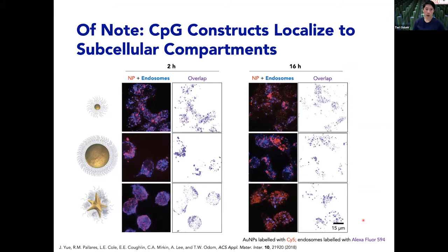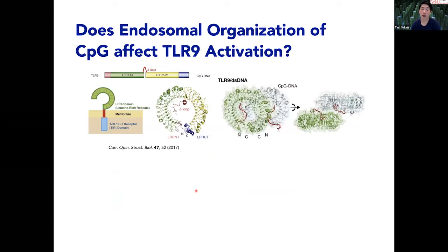And then one thing to note is that these CpG constructs, they localize to subcellular compartments. They will localize to endosomes, as you can see here, for 2-hour incubation or 16-hour incubation. These big areas are the macrophages, but you can see that even the distribution of the spheres versus the stars within the macrophages looks quite different. So we cannot understand this difference based on optical microscopy techniques, but we can evaluate this through some electron microscopy techniques. So the question we were interested in was whether the endosomal organization of CpG affected TLR9 activation.